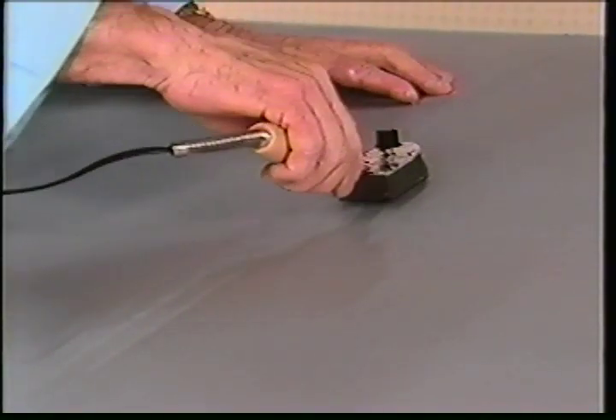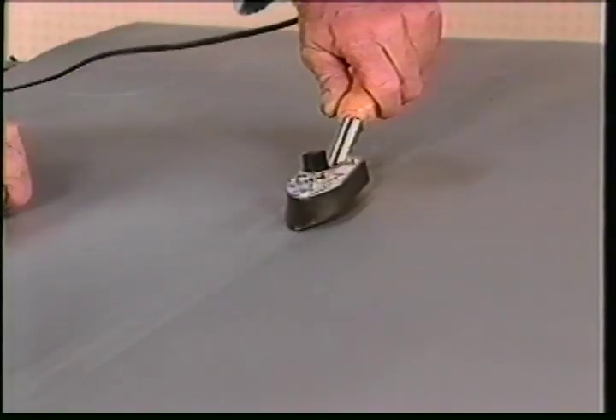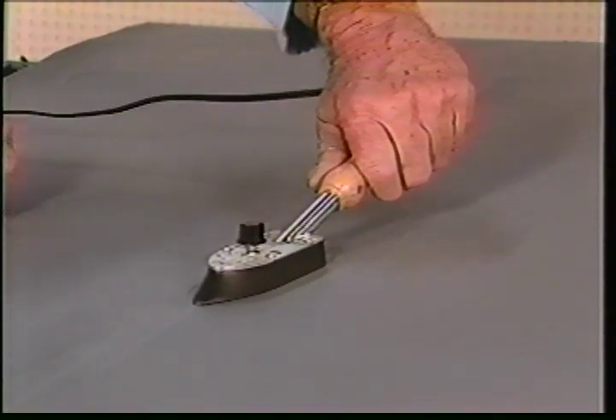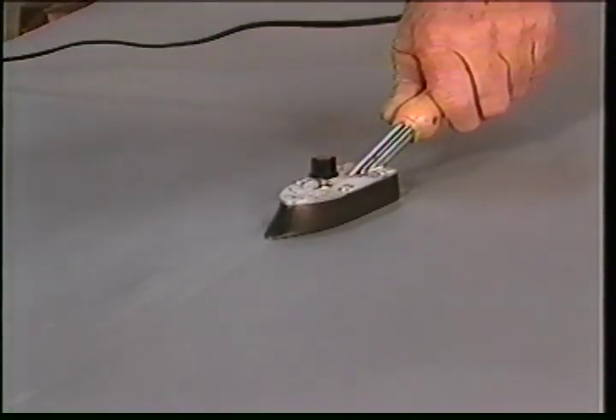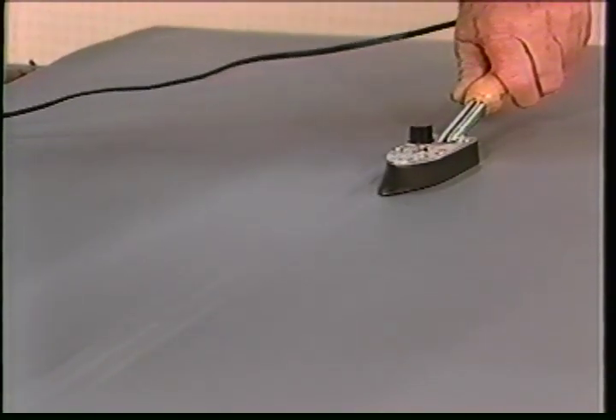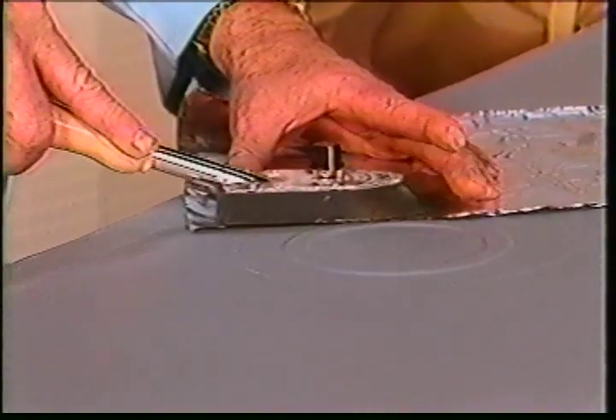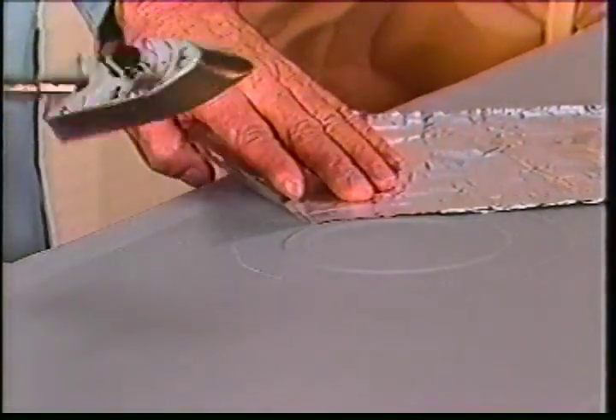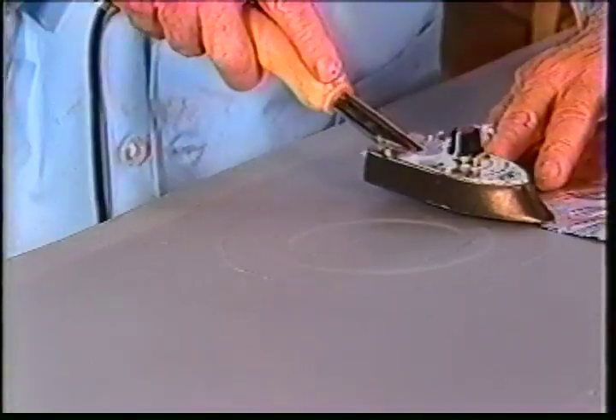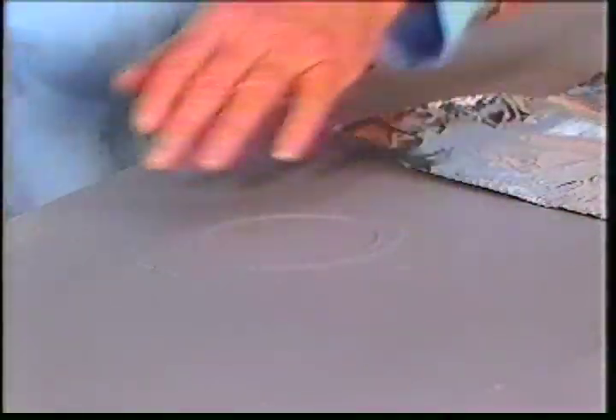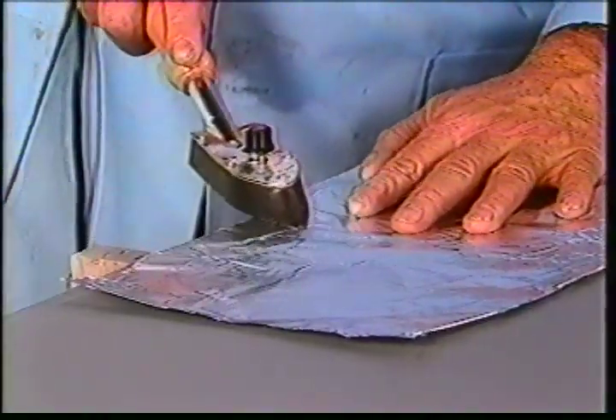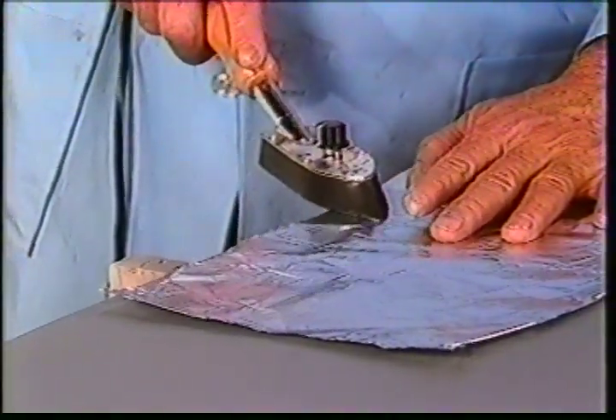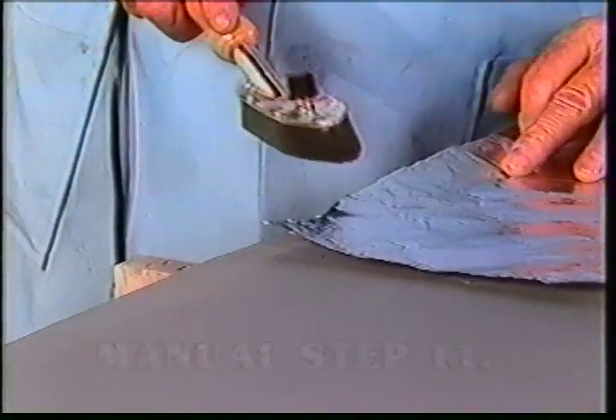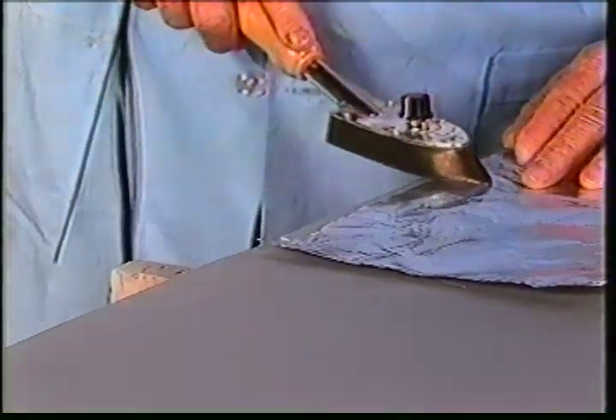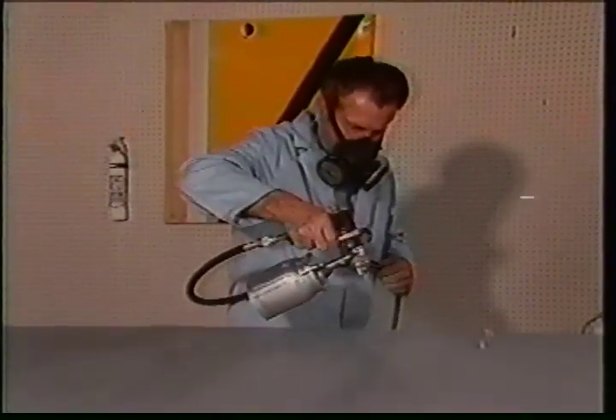After the first coat of poly spray is applied, a Teflon or Silverstone coated iron may be used very lightly to smooth tape edges previously overlooked. However, heavy pressure will imprint the coating. If it is necessary to use the iron to lay down loose edges or remove a small wrinkle, place smooth aluminum foil over the poly spray surface. An alternate is to remove the poly spray with polyfiber reducer on a clean rag, do the rework, then rebuild the coatings. After a thorough inspection and all touch-ups are completed, the wing is ready for step number 11, the second coat of poly spray to build a sanding base.